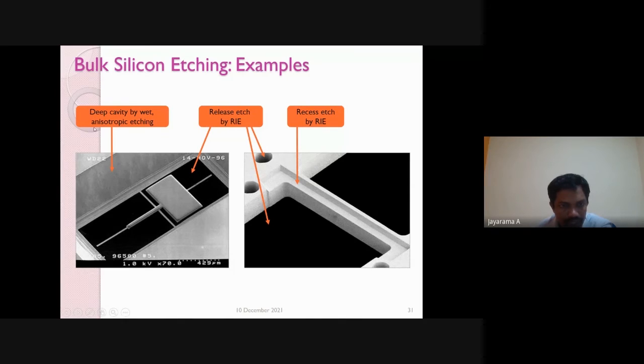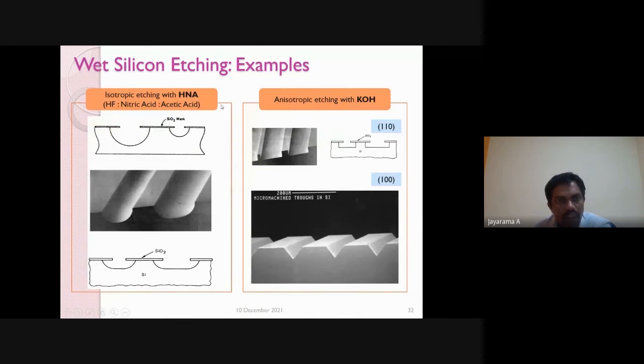Deep cavity by wet anisotropic etching, and this is another example of wet silicon etching. Here they use HNA, which is the combination of hydrofluoric acid, nitric acid, and acetic acid. Look here - this is isotropic etching, these are the same images after etching. The masking layer here is SiO2, used as a masking layer, and these are the images.